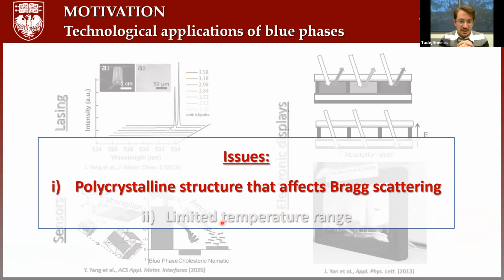This is the issue because polycrystalline structures mean we have many small domains, and each of these domains reflects its own color or its own wavelength, right? And that in the end affects the final reflection wavelength. So reflectivity is not as high and as effective as it should be. We can overcome this problem with the formation of a single crystal.